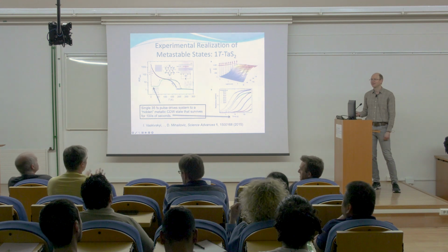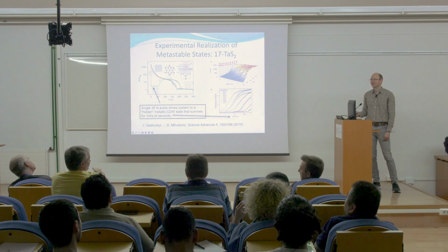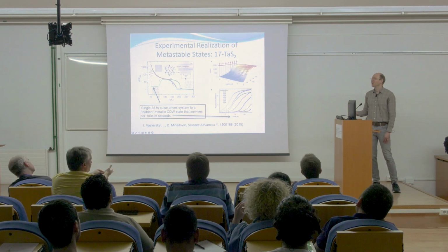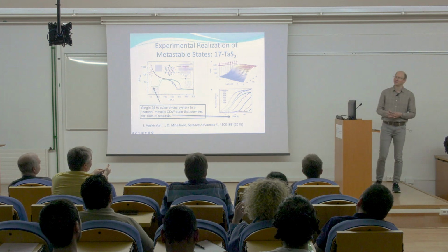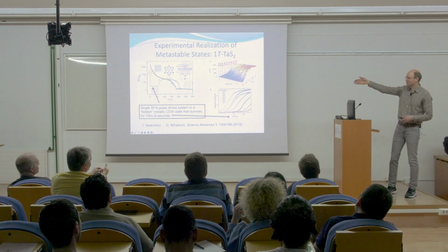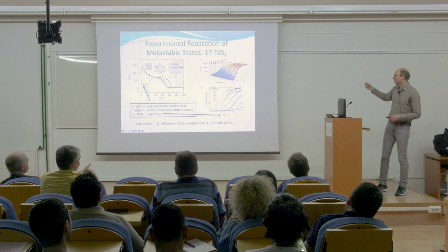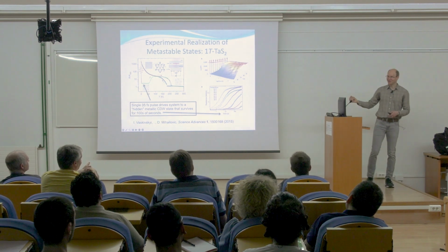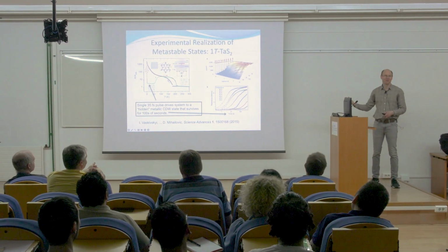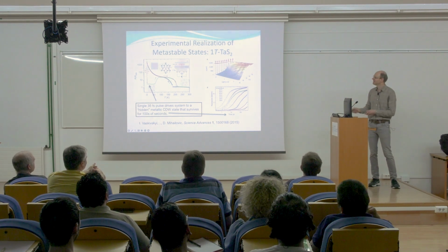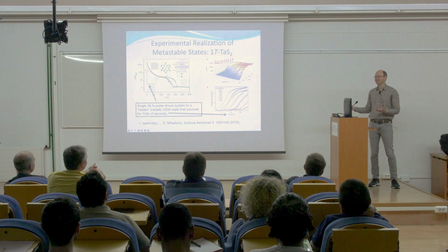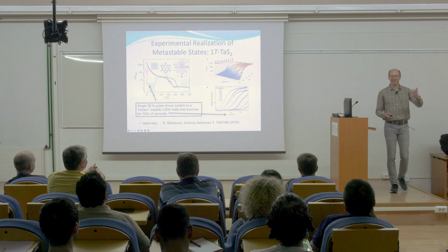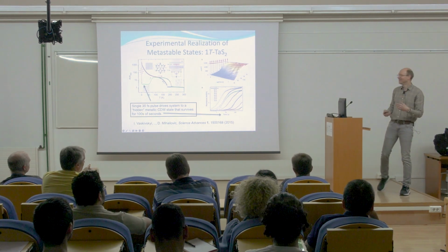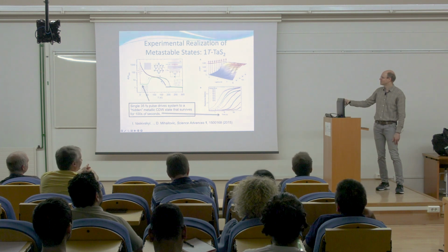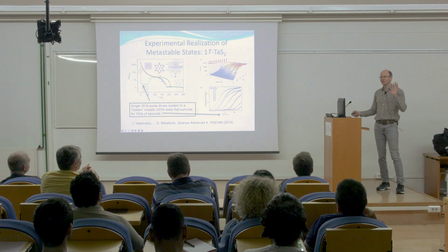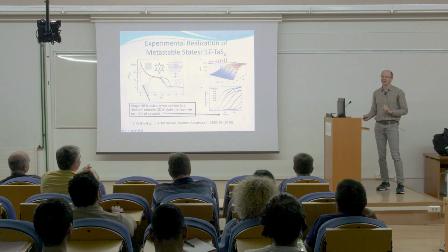I guess that regarding potential application, we were trying to push in the direction of having this type of effects closer and closer to room temperature. Yeah, exactly. That's another great point that you make, which is that this example is at such low temperatures it might not be practical for applications. But we proceed with what we have. If we can understand the low temperature situation, which from the point of view of theoretical modeling is easier in many cases, because our preference as theorists is to work at zero temperature first, and then later ask what the finite temperature corrections do. So the analysis is easier here, and also the experimental effect is more dramatic here. But it's true, we would like to push effects like this to room temperature for applications.